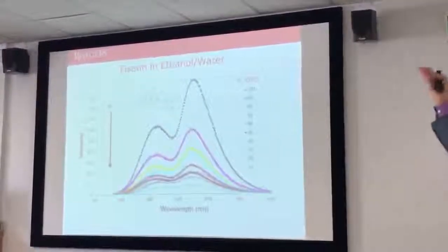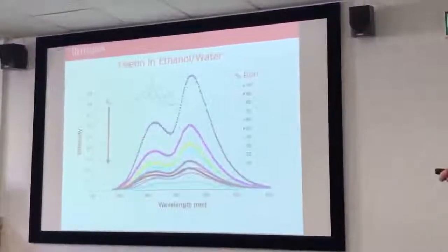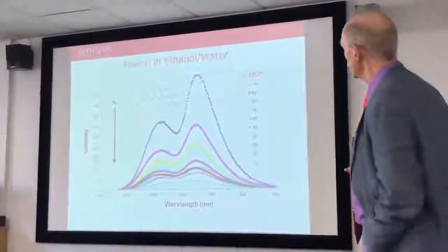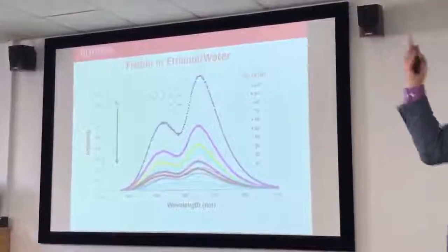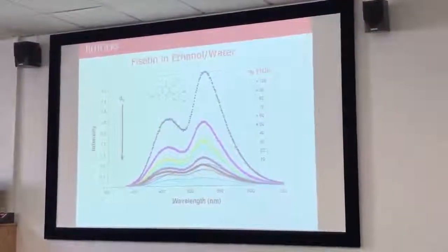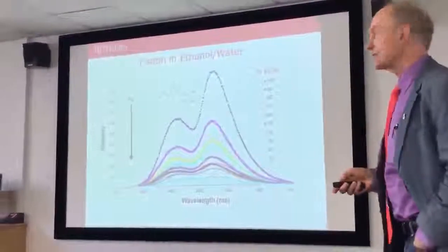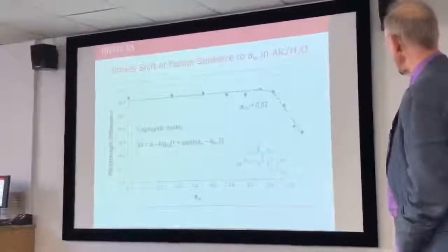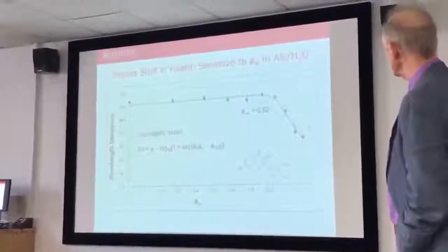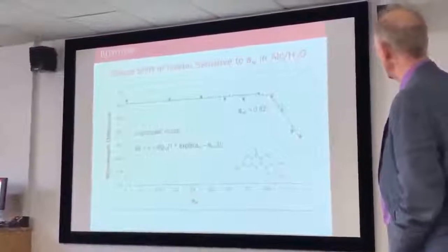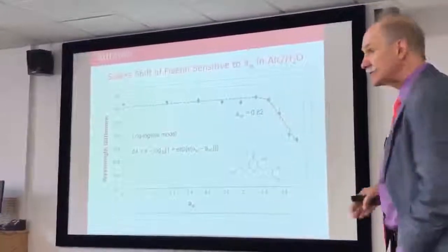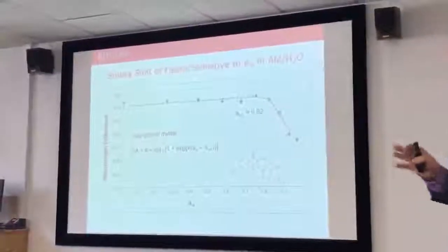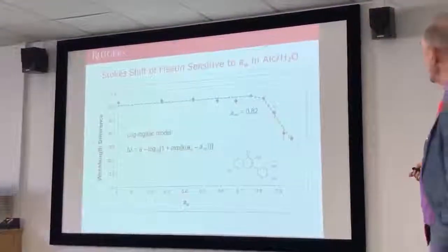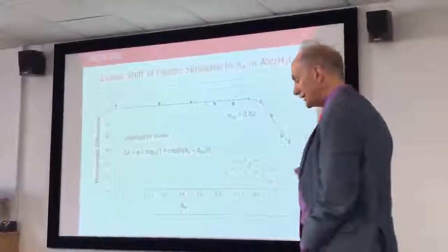But it's not natural; we can't eat that molecule. But we can eat fisetin, sort of. I mean, you could potentially eat fisetin, which is a naturally occurring flavonol found in foods. And we do the same thing, and with fisetin we see it's sensitive between about 0.82 and 1, which again is not a bad range. It's kind of an appropriate range. So these two probes at least are sensitive to water activity in alcohol water solvents.